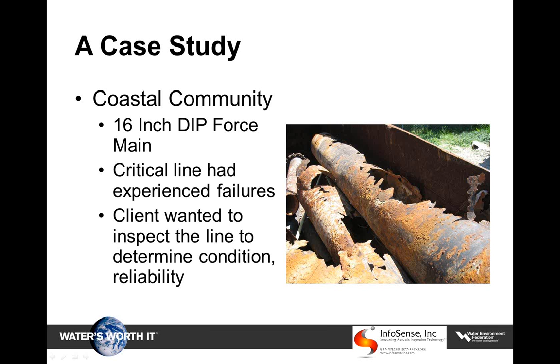It went from a pump station on the sound side of this barrier island, went inland up to a high point, and then ducked down and discharged at a wastewater treatment plant on the ocean side. The failures, as you see here, occurred in the crown of the pipe in the down gradient portion of the section where the hydraulic grade line dipped below the crown, and you get a lot of internal corrosion at that point. At this point, they still had about 4,500 feet of pipe that they felt was hopefully still in good condition, and wanted us to inspect it and determine its condition and what to do with it if they had problems.